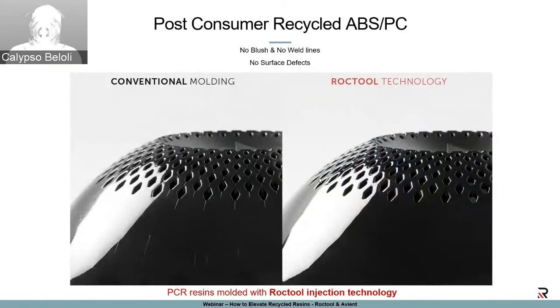Another example is ABS-PC molded with our Roctool. So it's a very complex shape with many holes. And as you can see in conventional, you have many weld lines and some defects from the materials. And with Roctool, you can see here complete elimination of these weld lines and no defects, black intensity, and high gloss surface. So it's important to understand that we can also do this on a complex shape, integrating our technology to achieve a premium look.